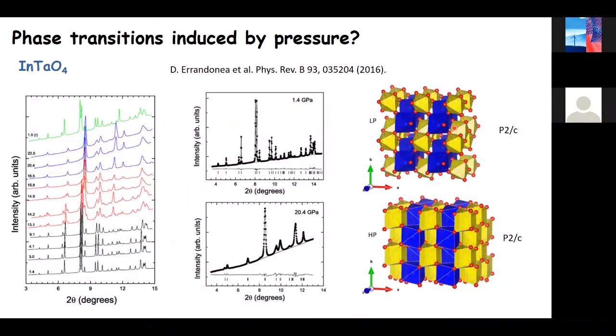If we go to the other compounds, which crystallize in the monoclinic structure already at low pressure, we have seen by X-ray diffraction that they can be explained by the low pressure phase until 9.1 GPa. But at 13.1, you will start to see changes. This red X-ray pattern corresponds to a pattern we have attributed to a phase coexistence between the low and the high pressure phase. And then the blue ones correspond to the high pressure phase. Under decompression, we fully recover the ambient pressure X-ray pattern, so the transition is reversible.